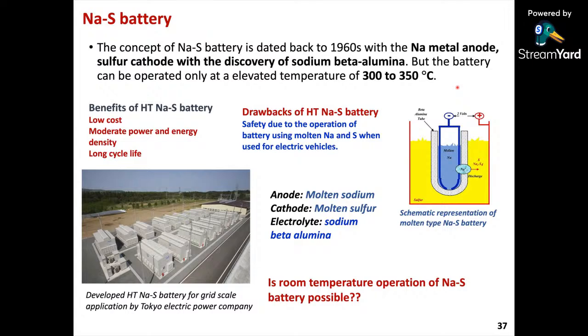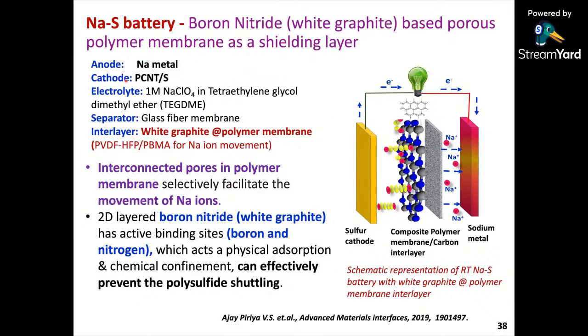So what we have done is that same cathode, we have used PCNT/S as a sulfur cathode. Okay, and we have tried different types of this interlayer with the anode of sodium metal, and finally we could be successful with a combination of the polymer PVDF PBMA polymer, which gives excellent ionic diffusivity, and white graphite, which is nothing but the boron nitride, which is having boron and nitrogen. Here I have shown boron and nitrogen. They have the capability of physically absorbing the sodium polysulfides.